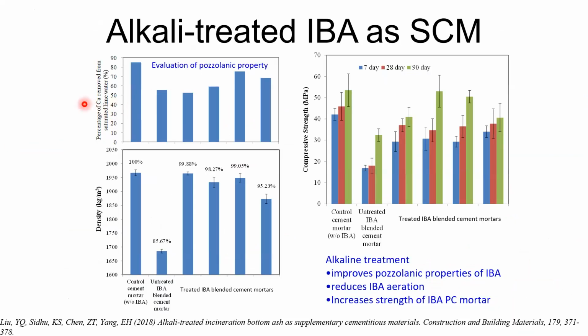Another initiative: when IBA is used as SCM, the major concern is gas generation, so we use alkali to treat IBAs. Using different types of alkalis and different concentrations, compared to the untreated one and the control without any IBA, we found that after treatment we can significantly remove the metallic aluminum, and therefore the density could be maintained. Also, by doing this treatment, the pozzolanic activity of the resulting IBA is improved compared to the untreated IBA.